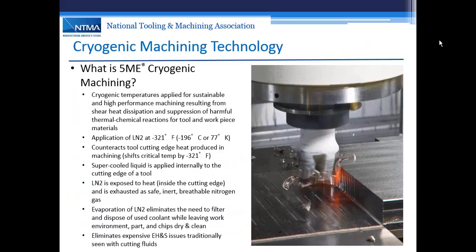Great. Okay, this is George Giorgio, the CTO for 5ME. What I want to do initially is just basically define what cryogenic machining is, the 5ME system. It's basically bringing a very, very cold cryogenic fluid, liquid nitrogen, which is at minus 321 degrees Fahrenheit or minus 196 Celsius, 77 Kelvin. We bring it through the machine tool, through an insulated tool, right to the cutting edge internal to extract the heat that would normally damage a cutting edge.